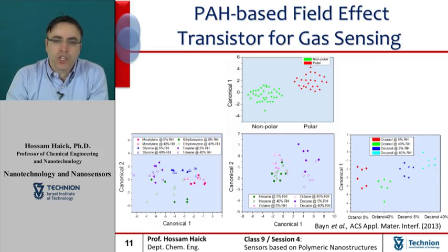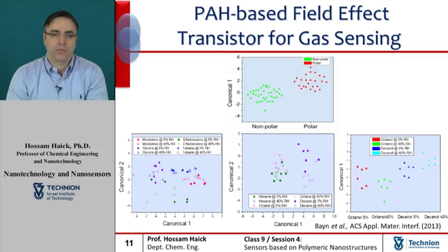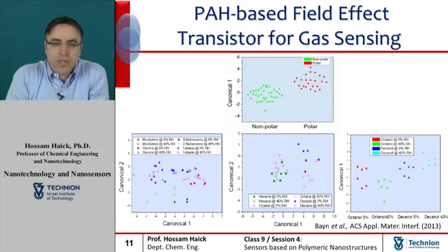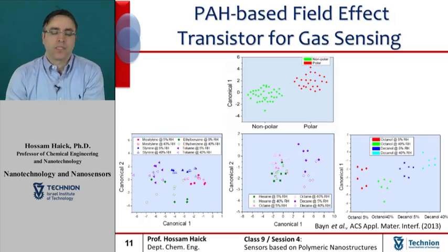Figure A on the screen shows discriminant factor analysis separating the polar material from the non-polar material. The accuracy level of the discrimination in this case was 80%. Figure B shows discriminant factor analysis separating the aromatic material, namely between mesitylene, styrene, ethylbenzene, and toluene, and in this case the accuracy level of the discrimination between these groups was 75%.